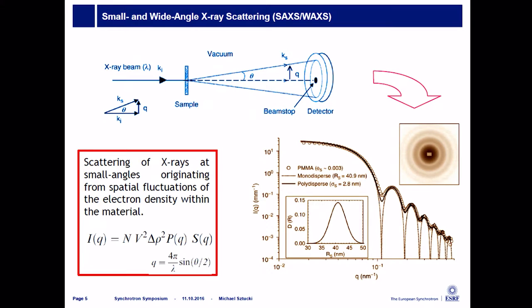The scattering intensity, when you look at the formula, is proportional to a form factor. So you can fit a certain form factor into it and get information about the shape of the particles — like monodispersed or more polydispersed spheres. You can also see interactions, which give rise to extra peaks. These are actually what you usually address as diffraction peaks.